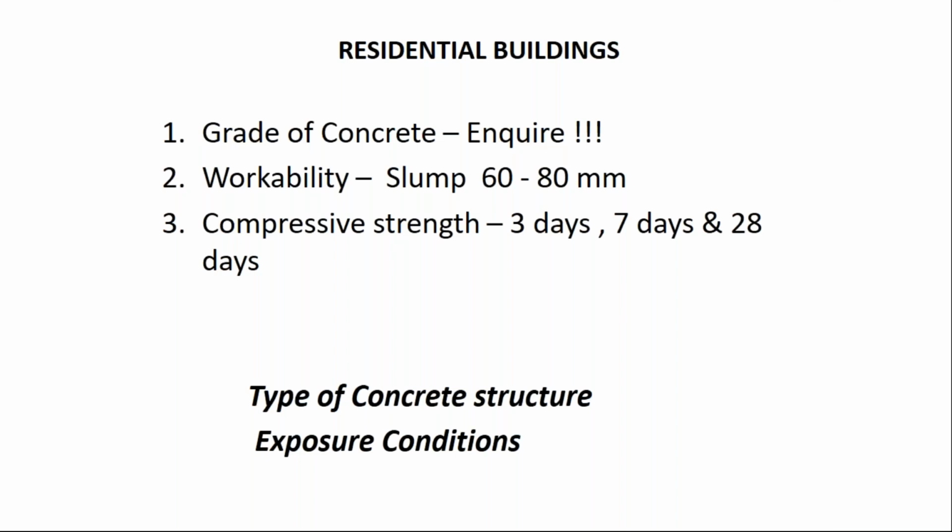Now this is what we typically do based on our experience with interaction with various construction professionals. As all of you know, we as an organization typically interact with various kinds of professionals. Normally you will find residential buildings make up the majority of them, and there, the first and foremost thing, if you go and inquire the grade of concrete, many of them would not be aware. The unorganized construction sector that is there in many of the places, they would go in for a nominal mix. Many of them have started using 1:1.5:3, because M20 grade concrete has to be used at least, that is the minimum grade of concrete, as all of us know.